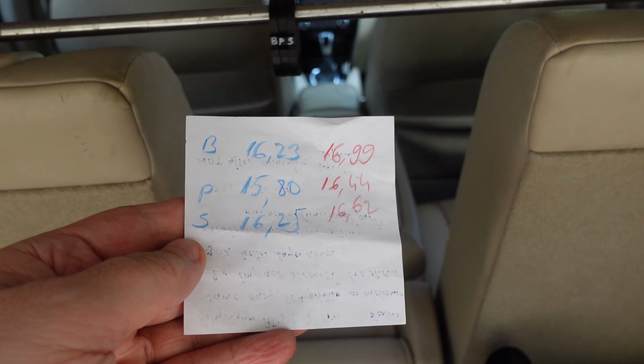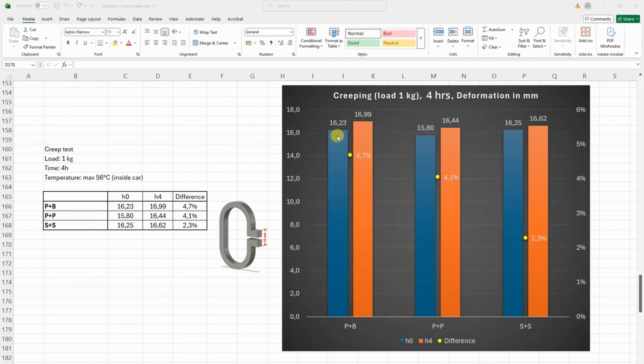Now let's analyze these numbers. This is the initial deformation, and this is after 4 hours, the distance between two reference surfaces. And the difference between the two in percentage is the creeping, and more or less on the Polymaker filament it is very similar, a little bit smaller printed on the Prusa printer, but significantly smaller creeping we can see on the Stratasys, one of the biggest advantages of this filament so far.